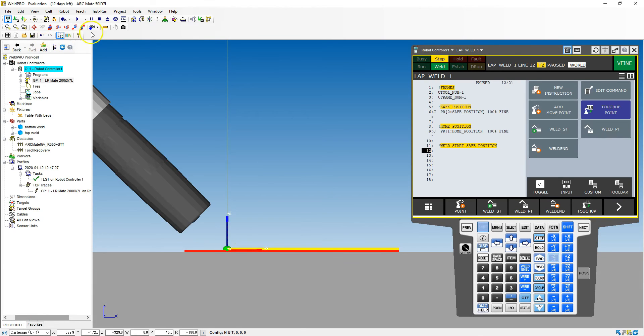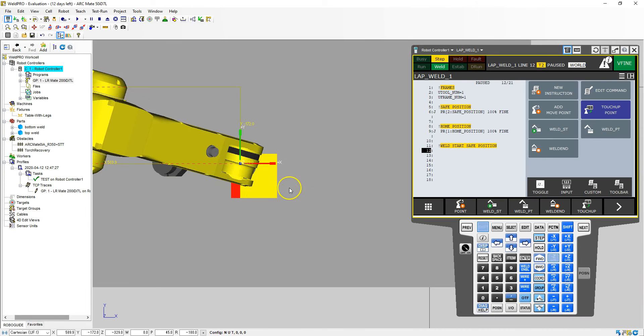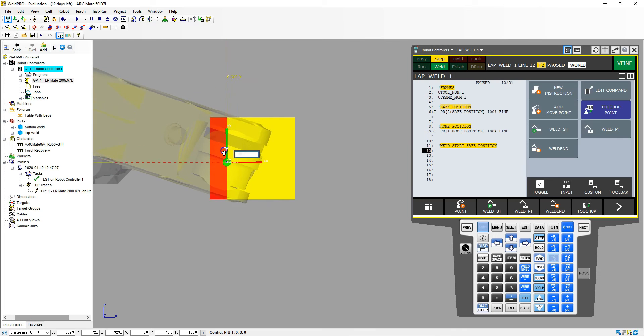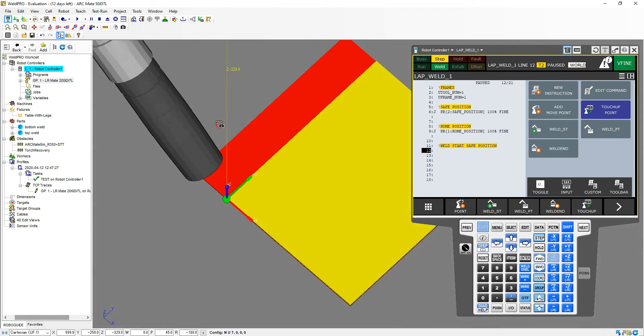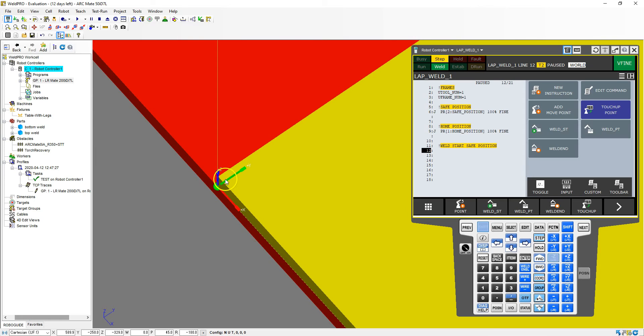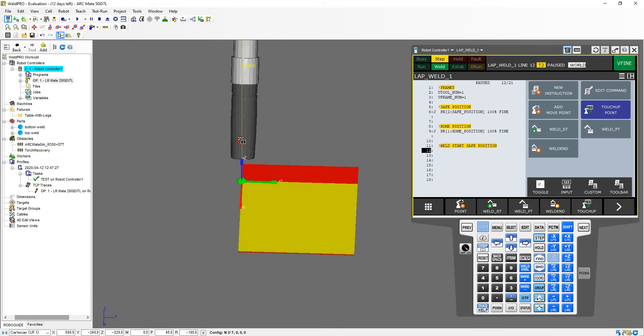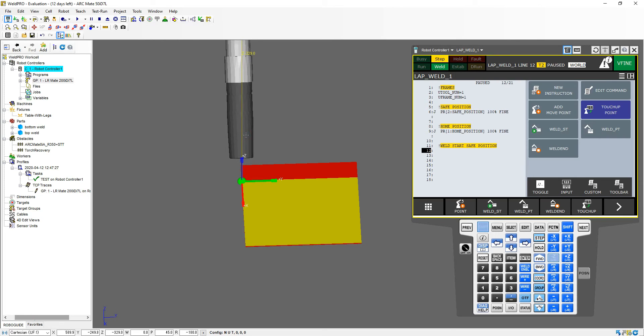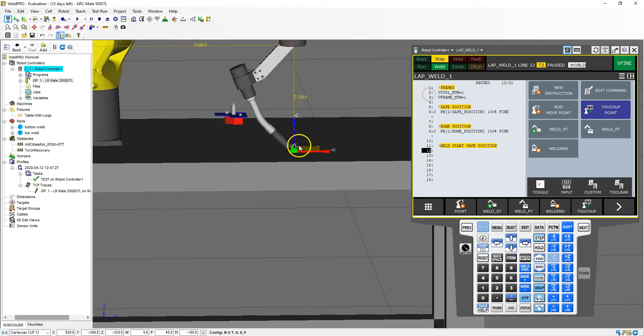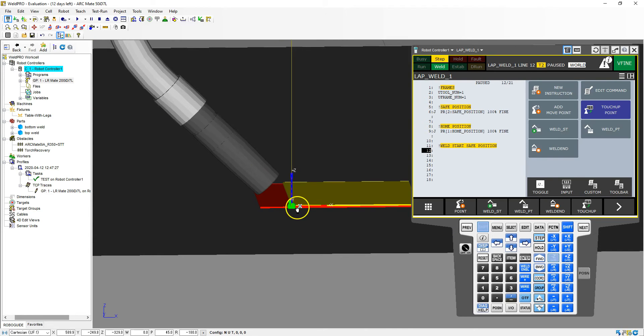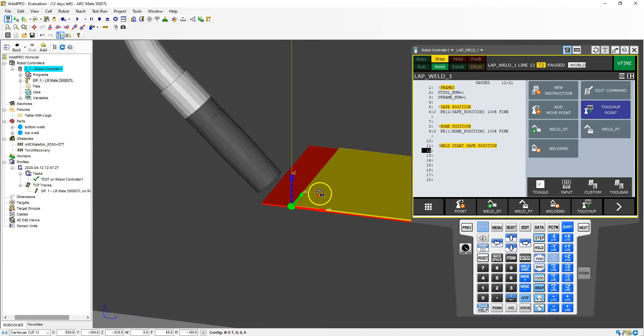Now I'm in place. I'll go to the top view to make sure I'm directly over where I'm supposed to be. My weld goes right to left — rotate around, make sure I'm on the end and go in just a hair. Now that I have this in position I'm going to rotate this so I have the correct angles. On our stick here we should be 45 degrees to the 90, so our stick is about 45 degrees — plus or minus a few. You don't need to get out a protractor.